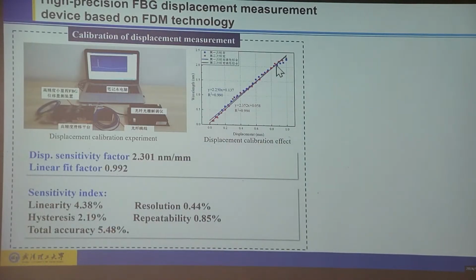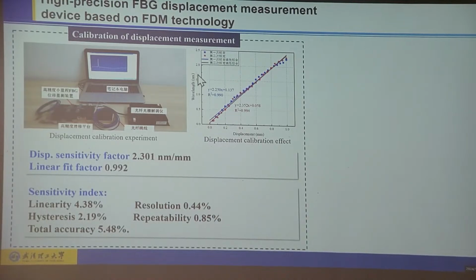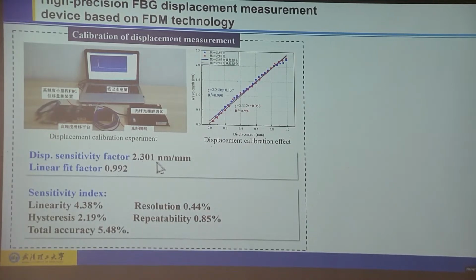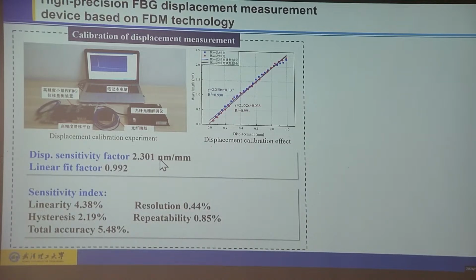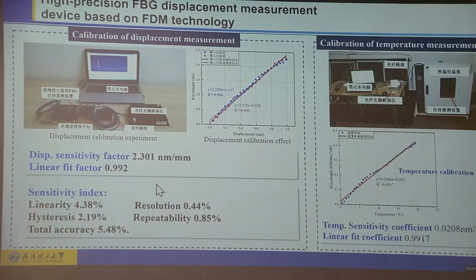So we do some calibration tests. We change the displacements, and we found this relationship with the wavelength shift, so we can understand the displacement sensitivity factor is 2.3 nanometer per millimeter. This is the sensitivity factor. And also we have this sensitivity index: the linearity, resolution, hysteresis, repeatability, and total accuracy is 5%.